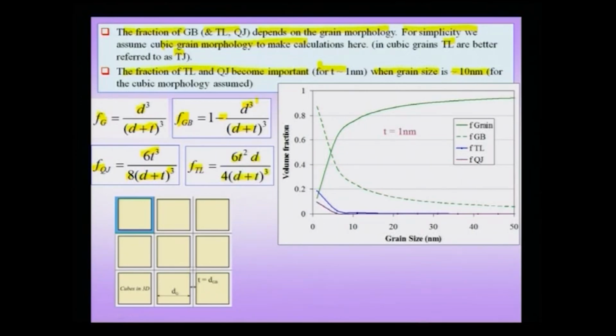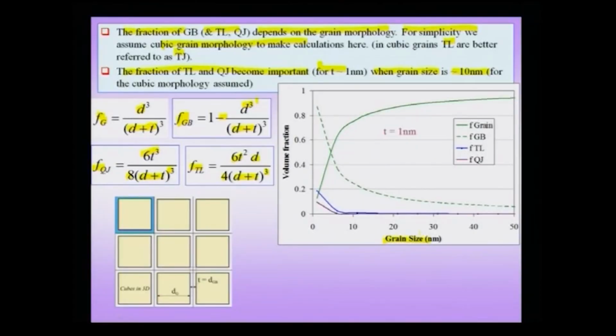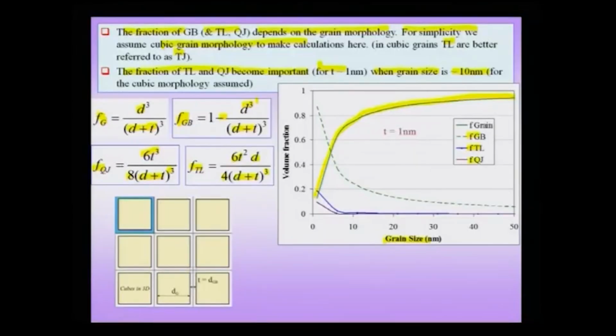Therefore, I have definite formulae for the fraction of the grains, the grain boundaries, the quadruple junctions and the triple lines. If I plot these functions as a function of the grain size, you would notice that this is the main function, which is the fraction of the grain, and the fraction of the grain seems to reduce as you go down to smaller and smaller grain size. That means that if the fraction of the grain is reducing, the remaining material is going to increase, which is now going to be the fraction of the triple lines, the grain boundary and quadruple junction, which you can see are increasing.